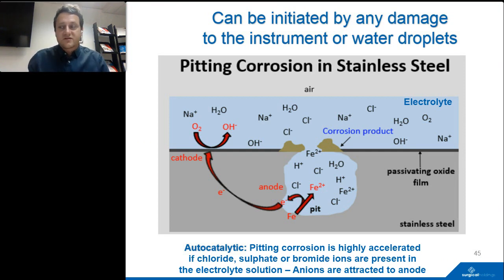And this is a big consideration for the surgical instrument maker, of course, because we have to ensure that instruments are passivated, and we do the best to ensure that they resist this sort of issue. But sometimes if an instrument is scratched, free iron can be released from the pit, where you see here. Pitting corrosion is highly accelerated if chloride is present.